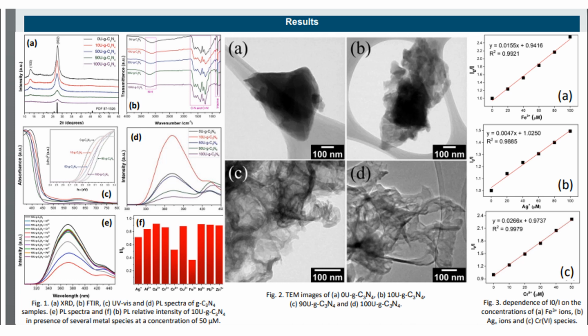The graphitic carbon nitride samples were also examined by UV-Vis diffuse reflectance spectroscopy to evaluate their optical properties. The UV-Vis spectra of the samples show strong absorption in the visible region, and a hypsochromic effect can be observed for urea-based samples compared to melamine-based samples, attributed to a lower conjugation during the polycondensation process. Furthermore, such a hypsochromic shift may be a consequence of quantum confinement effects resulting from the different particle sizes and geometric limitations to the electrons in the materials.